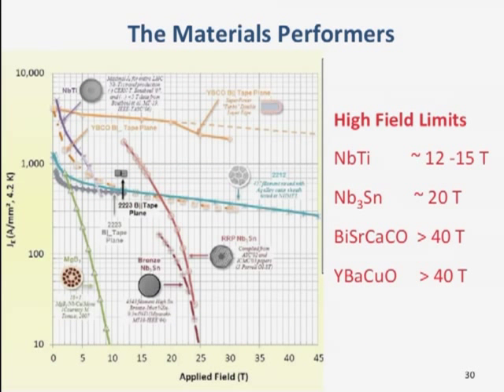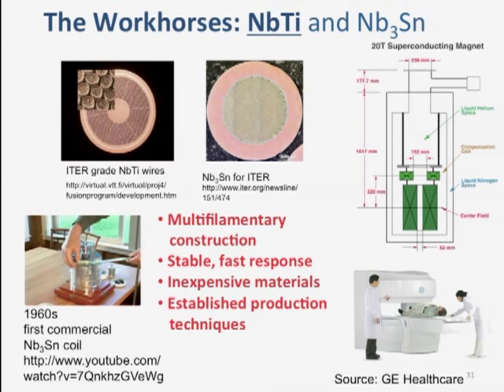I just want to point out the materials performers, that as far as the high field limits go, these high temperature superconductors actually have higher field limits than any other superconductor, okay, as long as you can pin the vortices. The workhorses, however, still remain niobium titanium, and in some cases where you need very high fields, you'll go to an A15 compound. And so these are examples here, et cetera. It's only the research magnets that use niobium-3 tin or niobium-3 germanium.